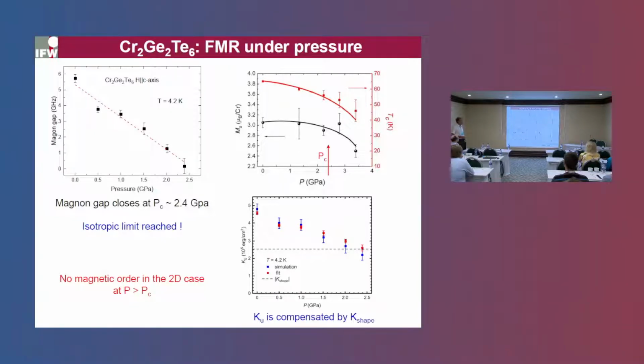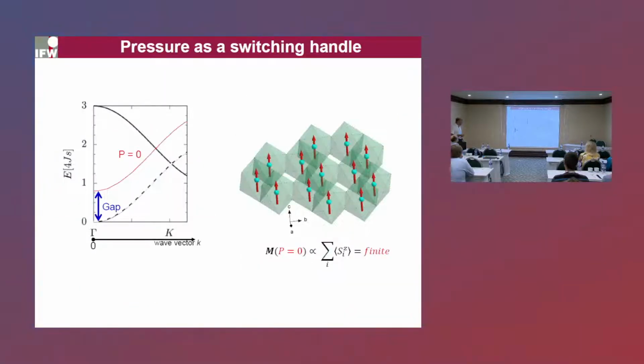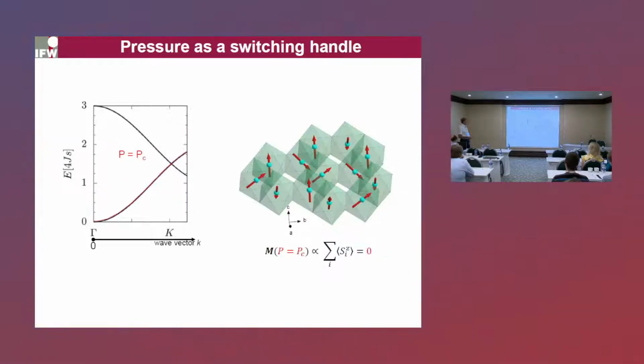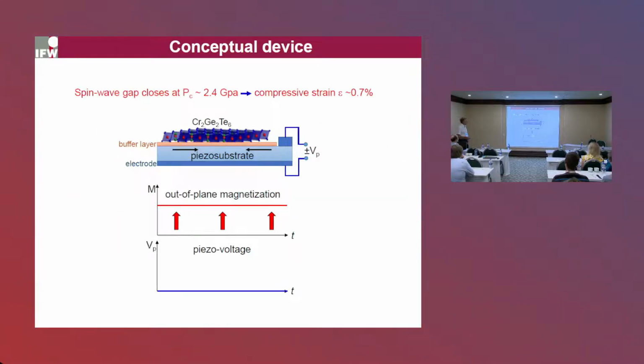So that means we have a handle. In the absence of applied pressure, we have a gap, and we potentially have, in the single layer limit, still a ferromagnetic order. But as soon as we apply pressure, we close the gap, and the order is destroyed. And so we can think of some potentially